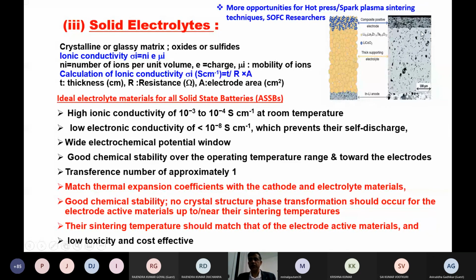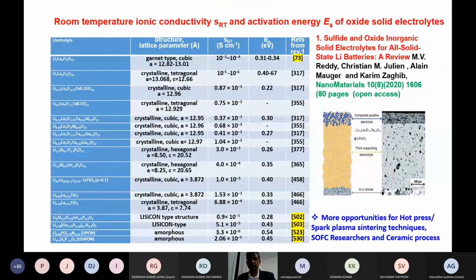So it is a little bit challenging for metallurgists and materials scientists to stop this, which means having a well-protected interface that won't react with the material. In fact, these are a lot of oxide-containing garnets. These are all samples at high temperature, nearly 800, 900 or 1000 degrees. You need to make a good sintered pellet to improve the conductivity.